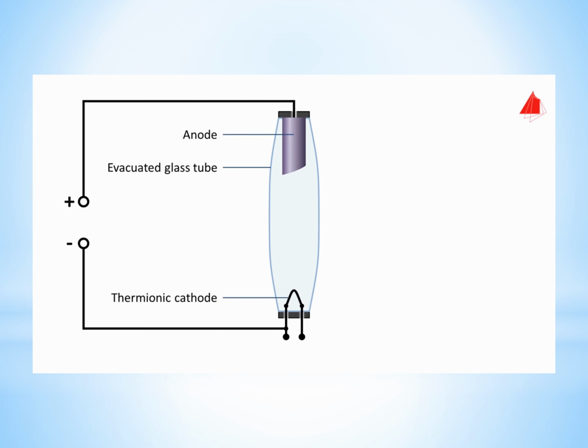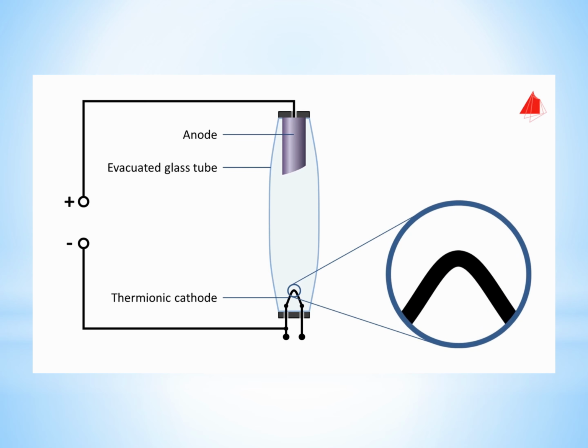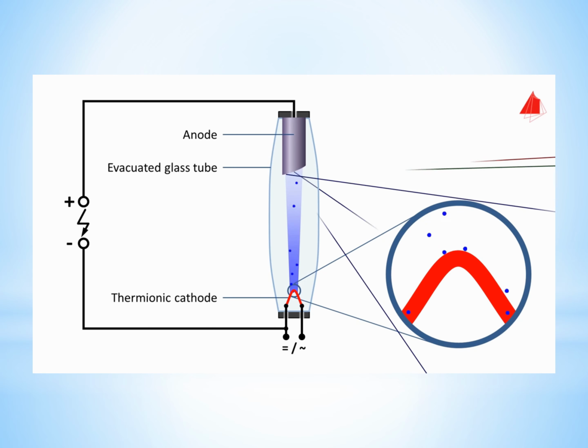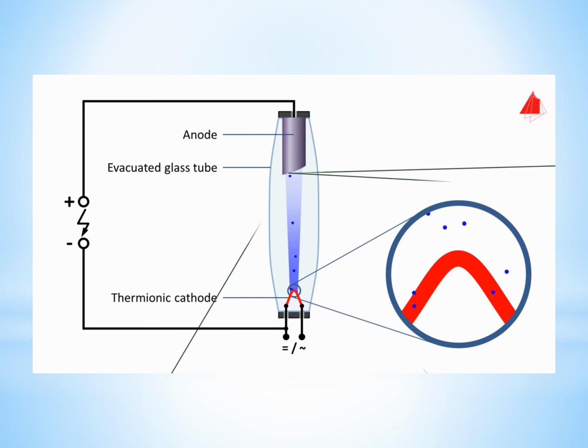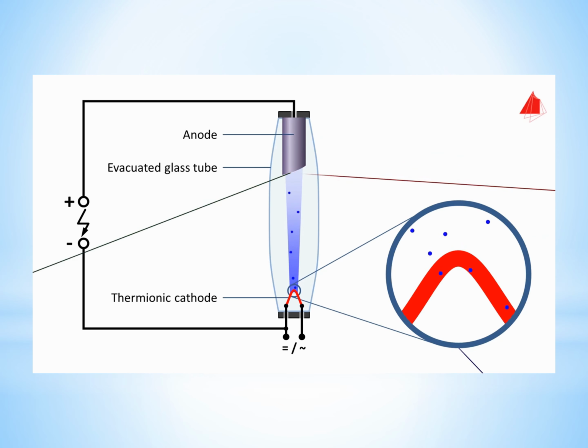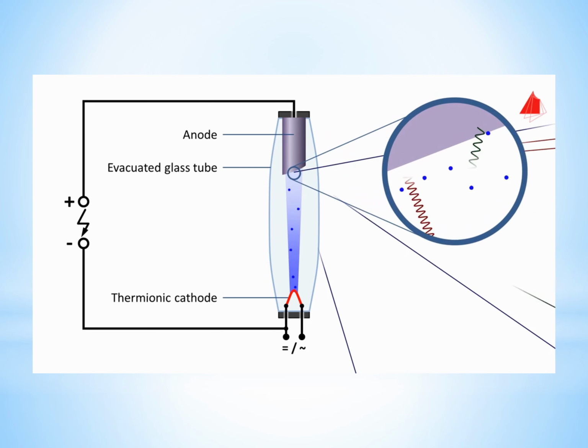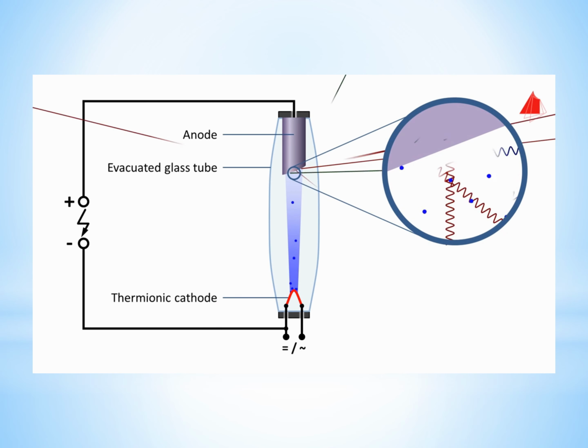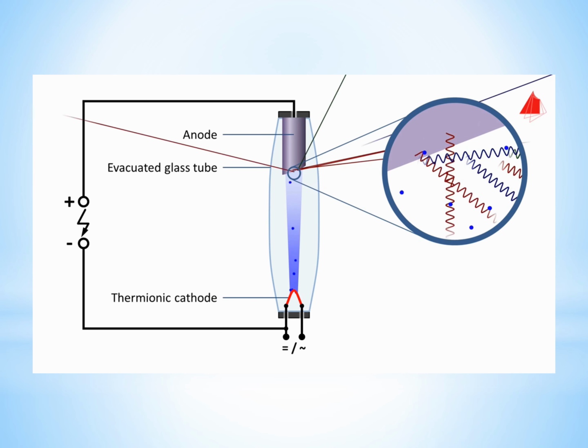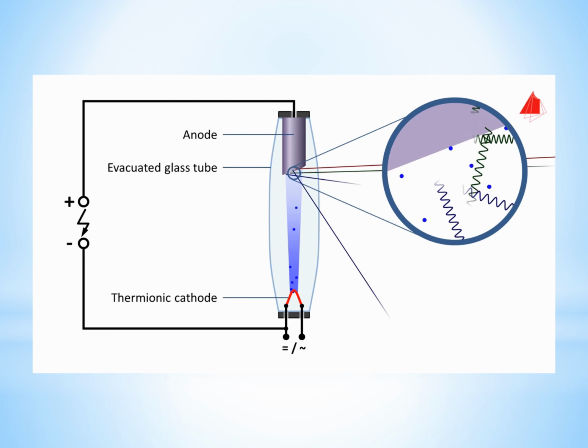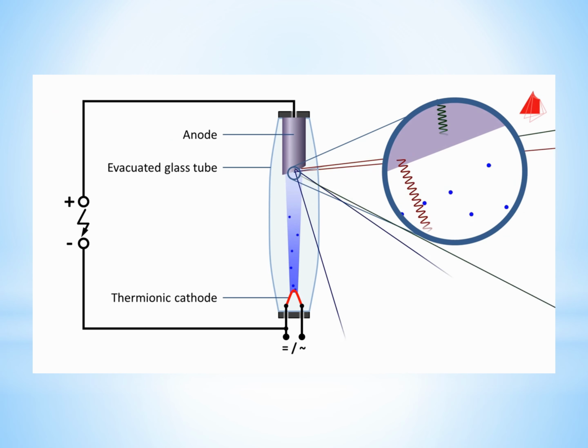From a high voltage source, the positive pole is connected to the anode, and the negative pole to the thermionic cathode. The thermionic cathode is now heated up by an electric current. The thermal movement enables some electrons inside the wire to leave the surface. This is known as thermionic emission. By switching on the high voltage, a strong electric field between the thermionic cathode and the anode is created. This strong electric field accelerates the emitted electrons towards the anode. An electron beam is formed. The electron beam collides with the anode at high velocity. The anode material slows down the electrons within a very short distance. This generates the desired X radiation, but unfortunately also a lot of heat, which has to be dissipated by cooling.